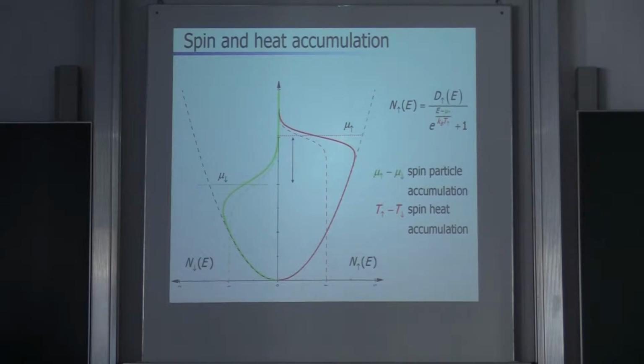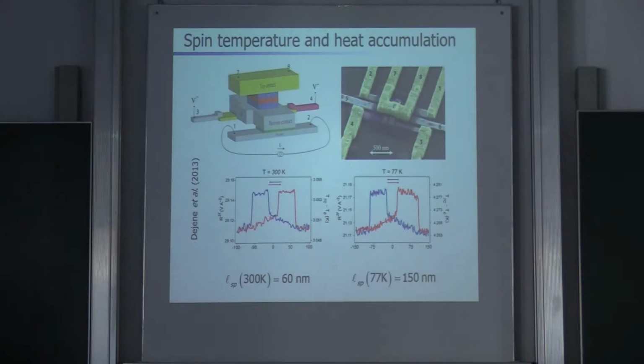Now, whether this exists or not is a bit complicated. Experimentally, it has basically been proven that it exists. These are experiments which have been carried out in the group of Van Wees in Groningen. It's a rather complicated three-dimensional structure, and you see a sketch here. The essential element here is a spin valve, F and F. What these experiments show is that the heat conductivity of this spin valve is different when the magnetization is parallel and antiparallel.